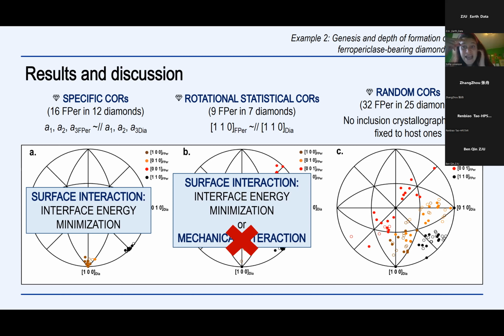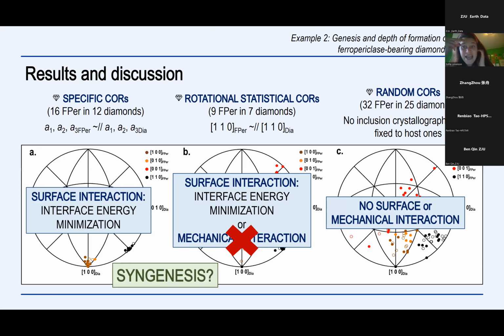Finally, the random CORs can suggest that probably no interaction occurred during the formation of ferropericlase-bearing diamonds. But what kind of information can different kinds of interaction give us about the formation of this system? In a very simple way, we can think that when we have an interaction, the inclusions are syngenetic. On the other hand, when we don't have interaction, the inclusions are protogenetic. But are we sure that in the case of ferropericlase, this information is enough to understand this?